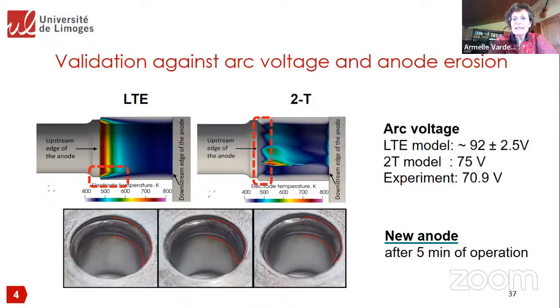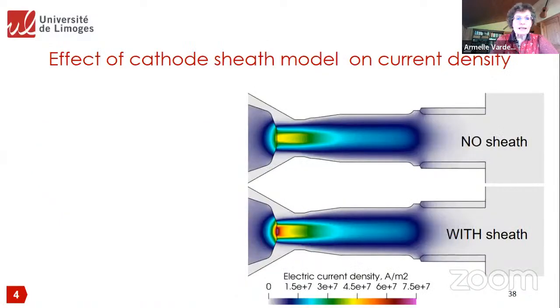Also, what we can do is to compare the arc voltage predicted by both models to the experimental one. With the LTE model, the predicted voltage is about 92 volts. With the two-temperature model, it's about 75, and with the experiment, it's about 71 volts. So you can see that we are getting closer to the experimental data. Now, what we can do is to implement this cathode sheath in the model. And the difference appears mostly at the cathode tip, of course, where the model is implemented.